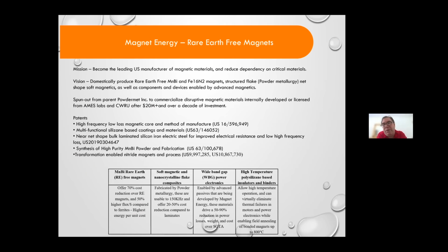Moving from there, we are also developing and using it as a binder for putting together high temperature magnetic materials. These are for rotors and stators in electric motors. Because of their stability to 600 C, the polysilazanes allow you to do field annealing and crystallization of metal amorphous nanocomposites and magnetic materials at up to 600 centigrade after fabrication. They're also excellent insulators, with very high dielectric strength.